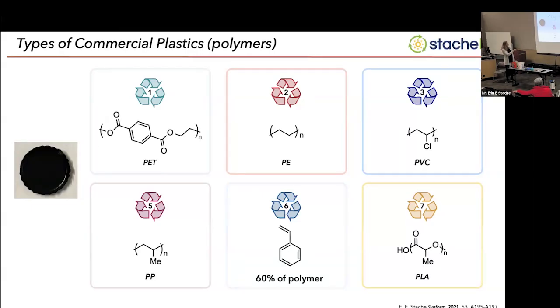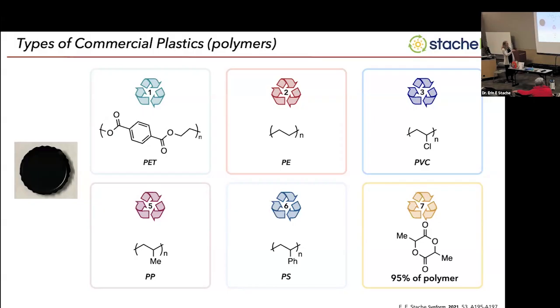We've shown this for polystyrene. We've actually gotten this yield up a little bit higher. I'll show you that in a few seconds using sunlight. And this works really well for PLA. PLA isn't one I've talked about very much, but it's kind of like PET. They're both polyesters.